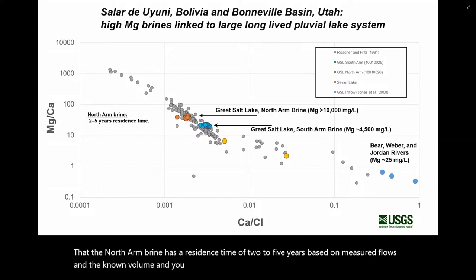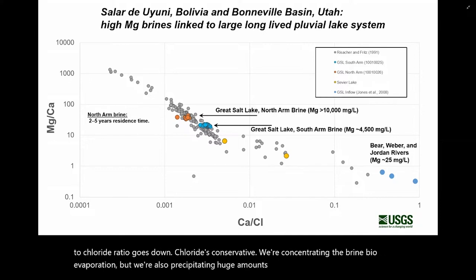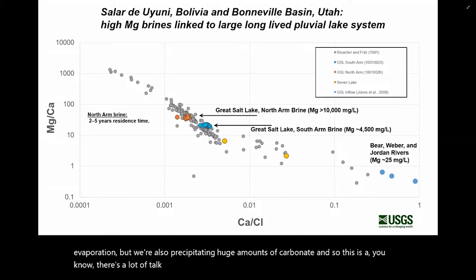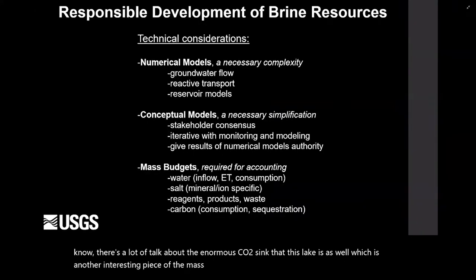And you see the magnesium to calcium ratio goes up as the calcium to chloride ratio goes down. Chloride's conservative. We're concentrating the brine by evaporation, but we're also precipitating huge amounts of carbonate. And so there's a lot of talk about the enormous CO2 sink that this lake is as well, which is another interesting piece of the mass budgets.